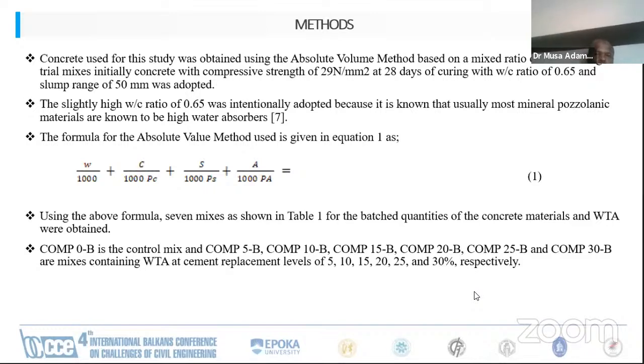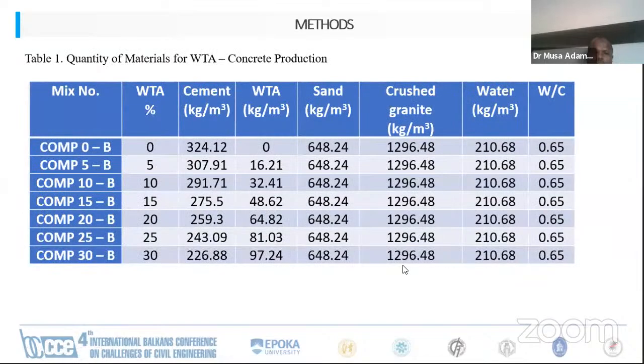So the absolute volume method is this, where W is water, C is cementitious material. And so using the formula, 7 mixes shown in table 1 for the batch quantities of concrete materials and WTA were obtained. So this is our table. We have our waste tire ash, the cement, then we have the sand, the crushed granite, water, and the water cementitious material ratio.